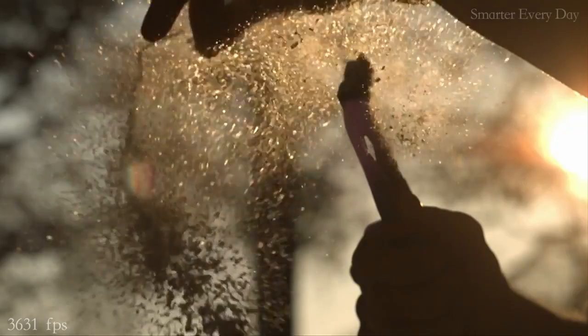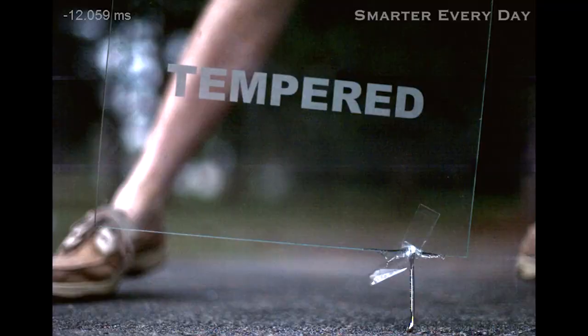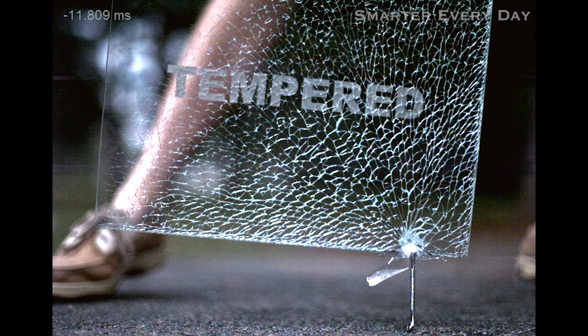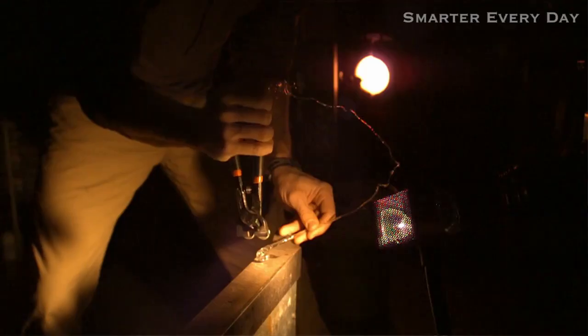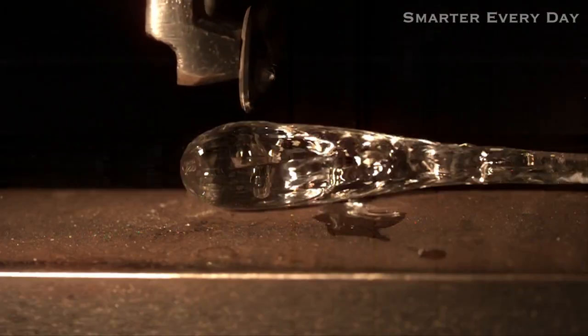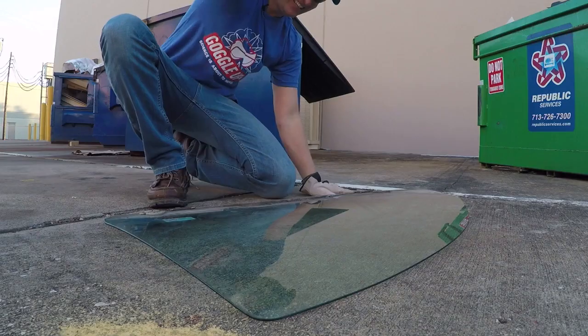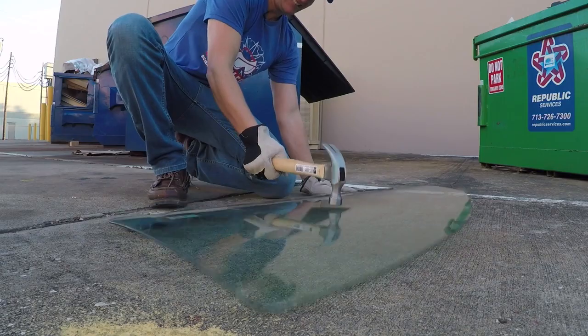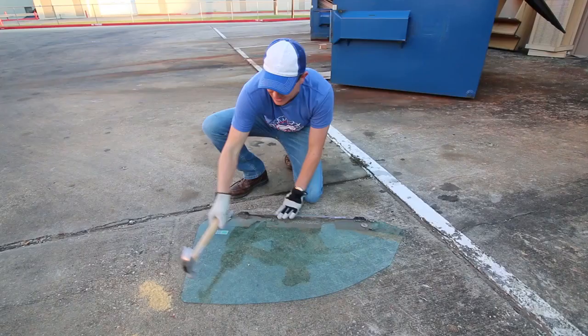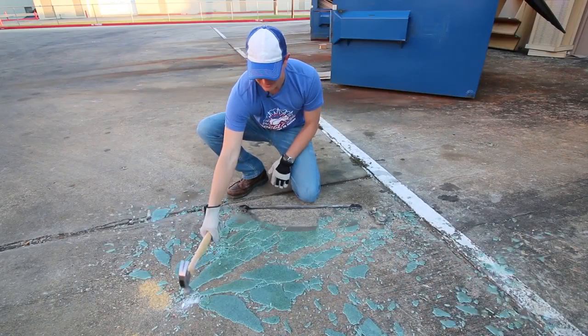Just like the Prince Rupert's drop, if you can get through that hard outer layer, it releases the tension and the failure front destroys the entire sheet of glass. On the Prince Rupert's drop, you have to get through the outside curved surface of the drop to release the tension, but on a car window, you have to get through the flat tempered surface to release the tension. With a sheet of glass though, we have to start it along one of the edges.